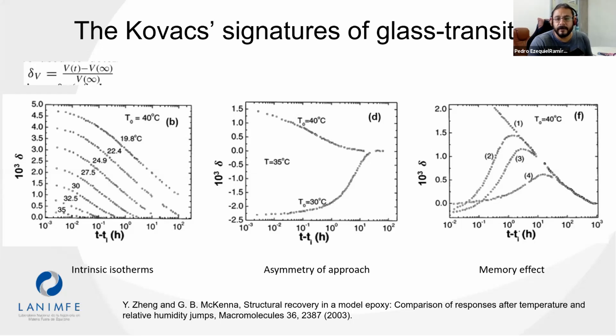Finally, the memory effect experiment consists of performing a sudden cooling to a final temperature, but in the middle of the relaxation process, the system is subjected to a sudden warming to an intermediate state with a temperature in between the initial and the final state. Such an experiment shows the non-exponential behavior of the structural recovery and the dependence of the kinetics on the thermal history. The relevance of these observations lies in the fact that several glass formers present them independently of their microscopic composition.